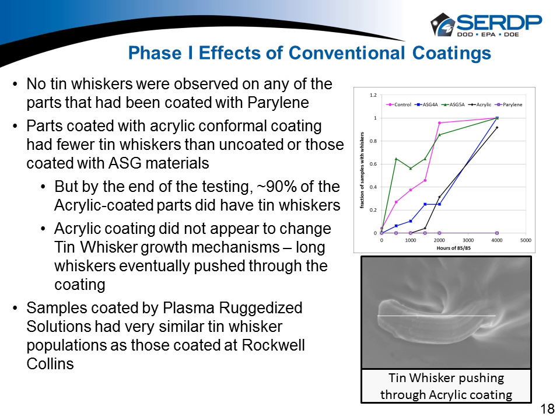The other thing we made sure we included is looking at the conventional coatings. We had both Parylene and acrylic. Those are two big primary coatings the industry uses. What we noticed is that both these coatings had fewer whiskers initially than a lot of the coating variables we looked into. But what was going on is the whiskers are growing under the coating. With our measurement technique, I didn't count a whisker until I could clearly define it as a whisker. So they really had to grow and poke up through the coating before we counted them. You can see here on the right on slide 18, this is a whisker that hasn't quite completely penetrated out of the coating.